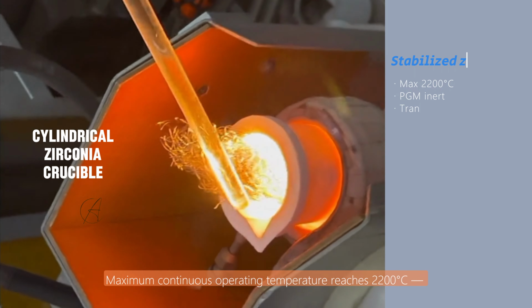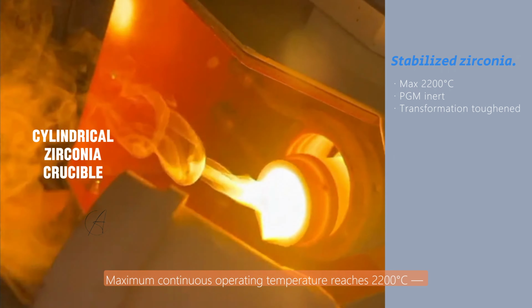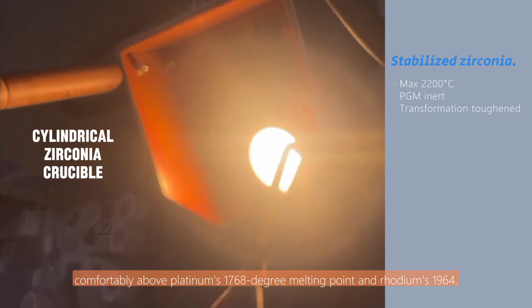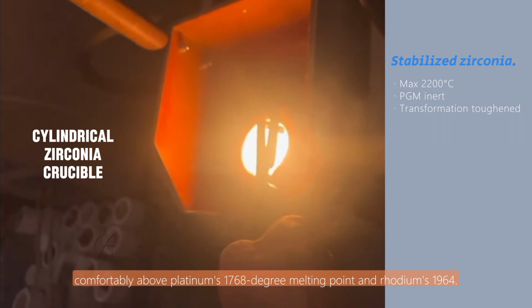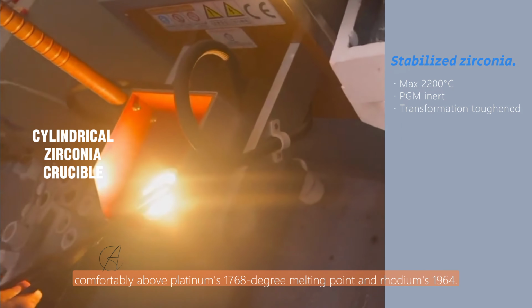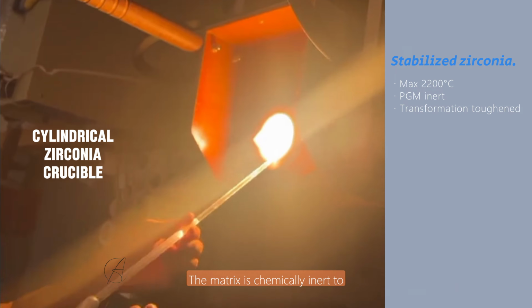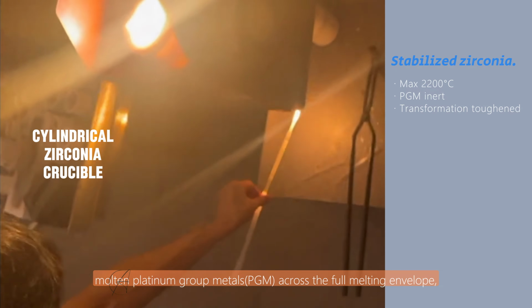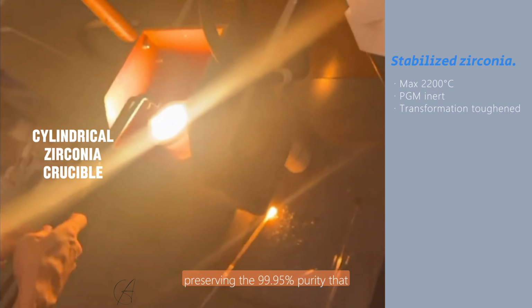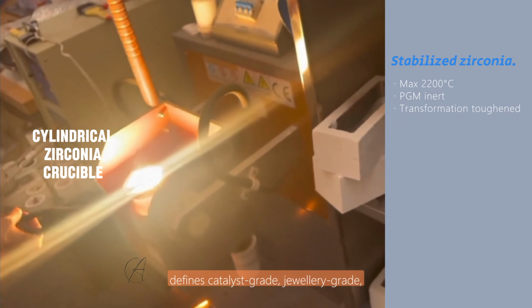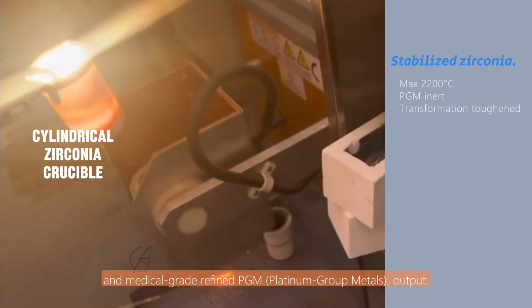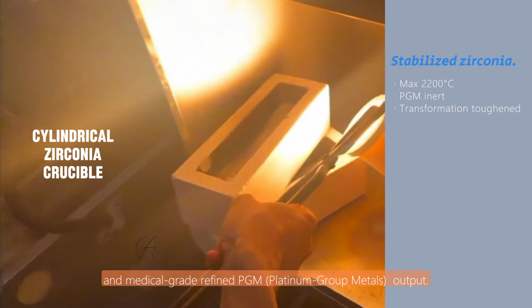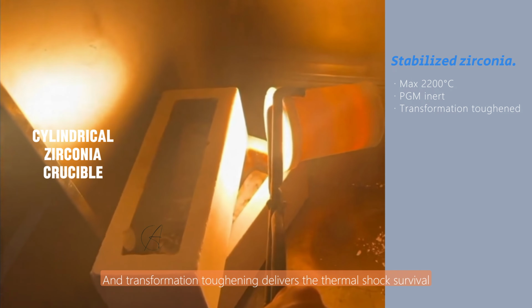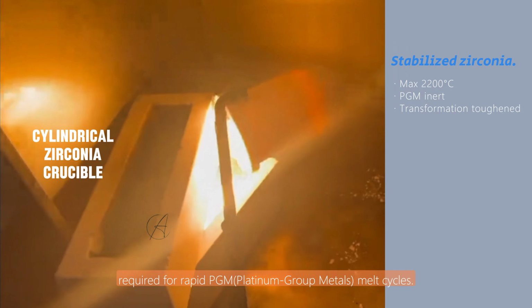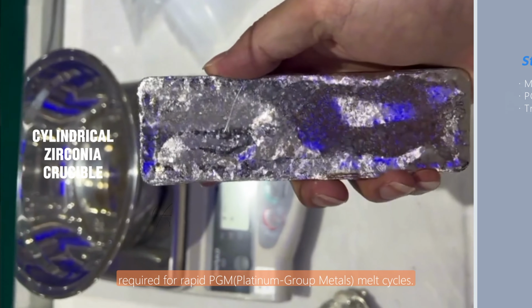Maximum continuous operating temperature reaches 2200 degrees Celsius, comfortably above platinum's 1768 degree melting point and rhodium's 1964. The matrix is chemically inert to molten platinum group metals across the full melting envelope, preserving the 99.95% purity that defines catalyst grade, jewelry grade, and medical grade refined platinum group metals output. And transformation toughening delivers the thermal shock survival required for rapid platinum group metals melt cycles.